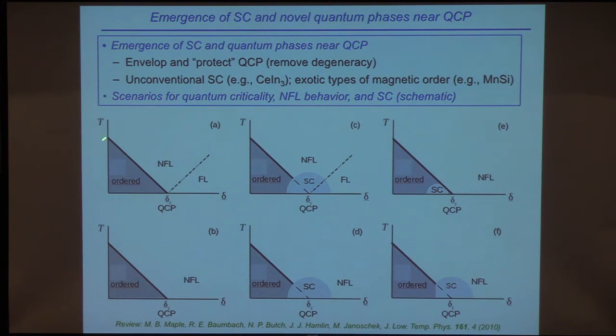So this is just schematic. So here would be the classic situation. You suppress some second order phase transition to zero. You find a non-Fermi liquid behavior in this region. It crosses over to a Fermi liquid right here. Sometimes, for reasons that I don't think anyone understands, you find that the non-Fermi liquid behavior extends out to high values of this control parameter without any readily identifiable quantum critical point. And then, interestingly, in this scenario, you sometimes see a dome of superconductivity that envelops the quantum critical point. And you can see it for this case as well.